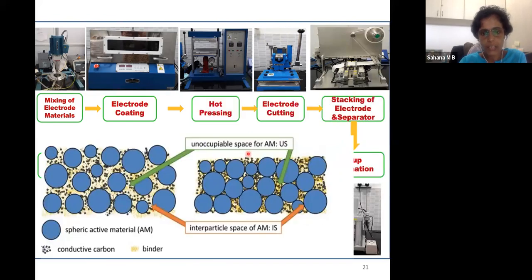And as I told you, there is a calendering. Using a hot press, we calender it. You can see that when we just coat the slurry on the current collector, the blue circles correspond to the active material, the small black circles correspond to conductive carbon, and the yellow ones correspond to the binder. When we dry, you can see that the distance between the active materials or the conductive carbon is quite high. So after drying, you will have a lot of pores.